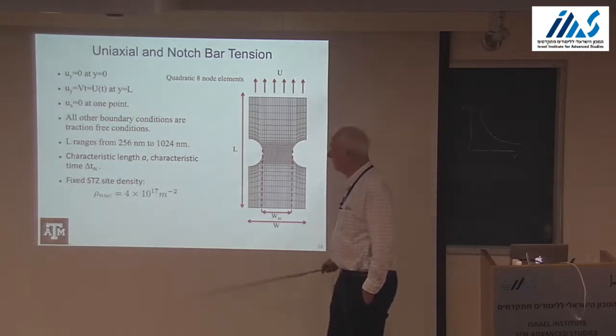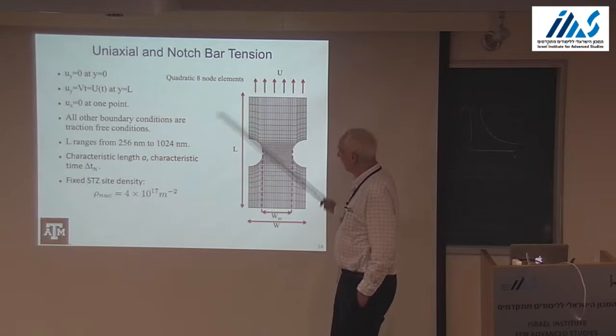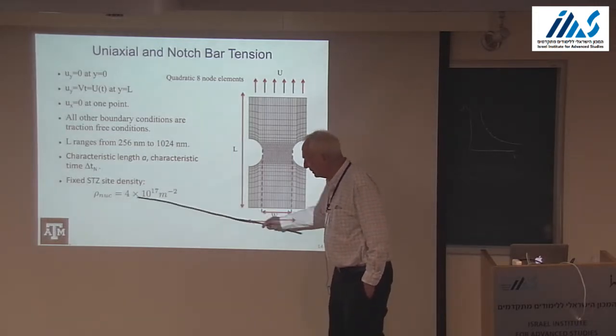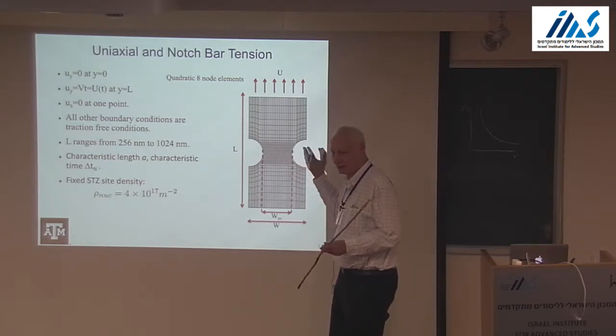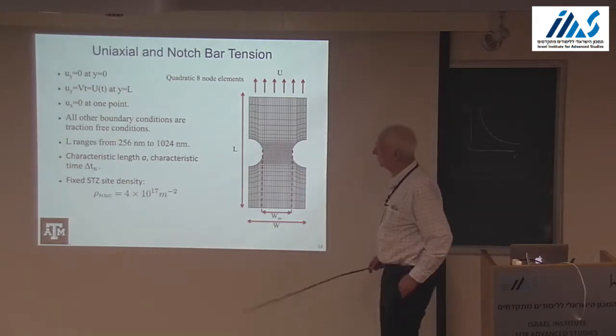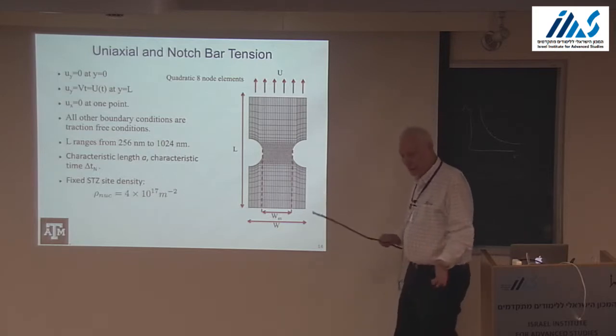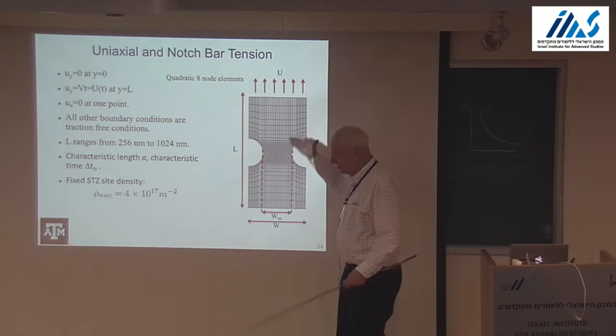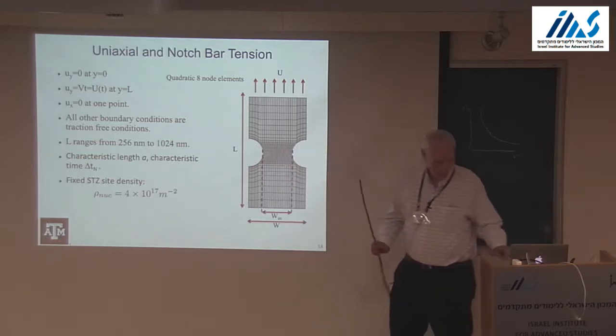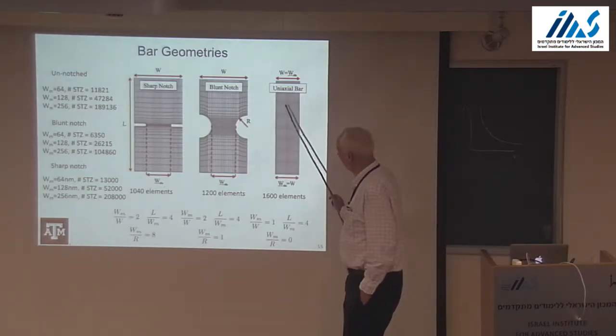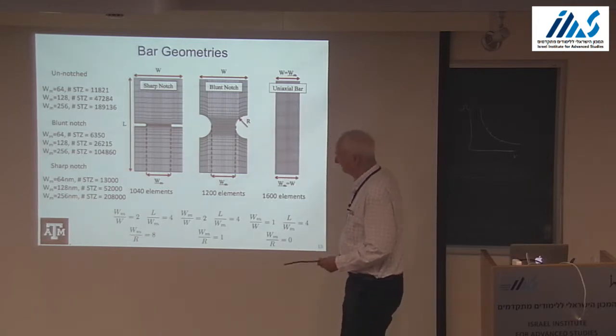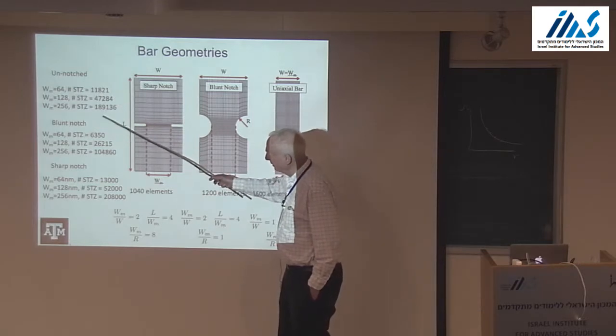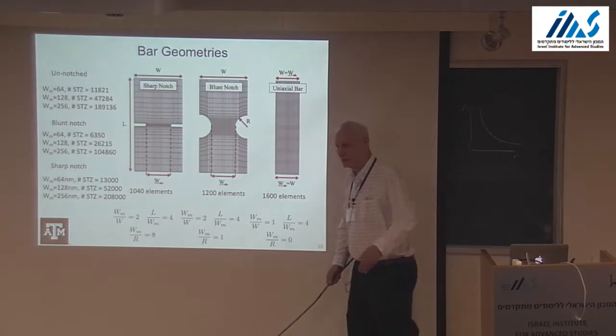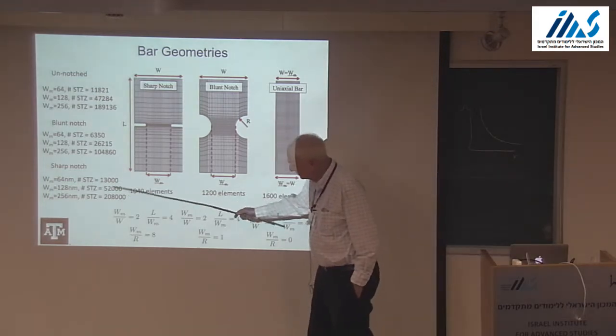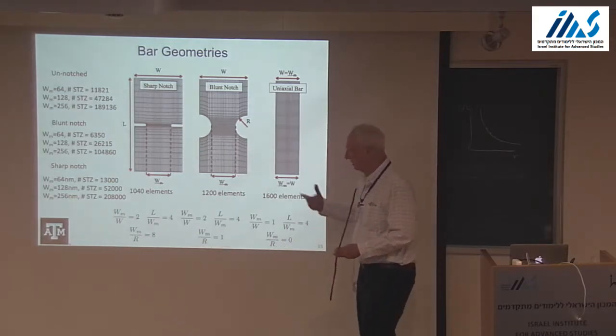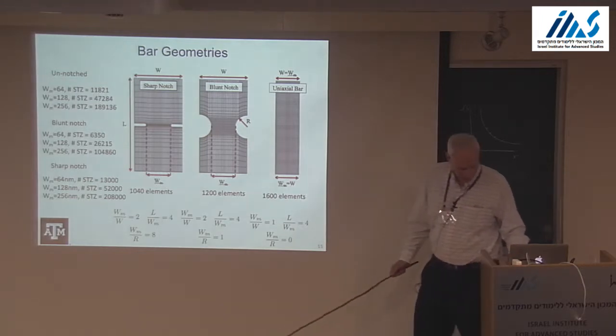So I'm going to do very small things, micron, quarter of a micron size, notch bars. I'll show different notch geometries. Fixed density, about a half of the maximum packing density for the size that we have. And this is just going to pull on this. In the first part of the talk, tension and compression just change the sign, so there's no inherent difference. We're going to look at a plain, unnotched bar, a blunt notch, and a sharp notch. The number of STZs, depending on the size, can go up to close to 200,000. This is just to show that we can have 10 times or more potential STZ sites than we have finite elements, unlike in the methods available up till now.